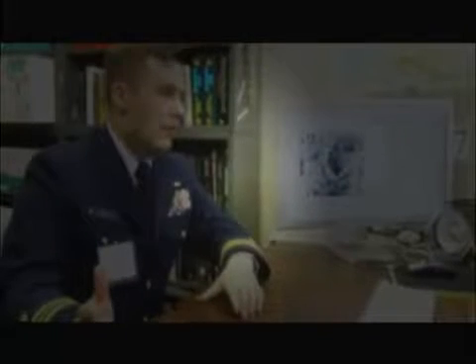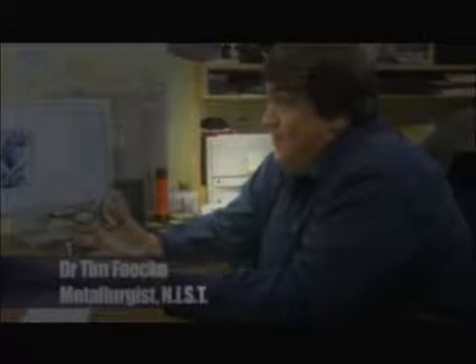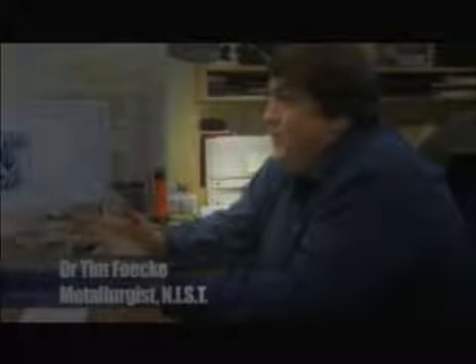Is there any problem with the manufacture or the condition of the steel plating on the Titanic? We've run tests on some Titanic steel ourselves, slow bending in ice water. Foecke subjected the samples to rigorous mechanical and chemical analysis and scanned the surface of test pieces using electron microscopes. His conclusion was plain. The steel was reasonable quality for the time and was not unusually brittle, even at low temperatures. If there was a flaw in the materials, it must be somewhere else.